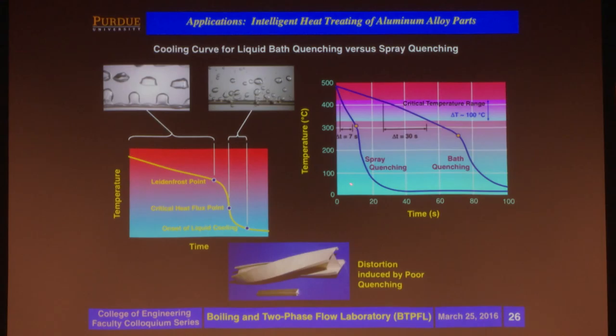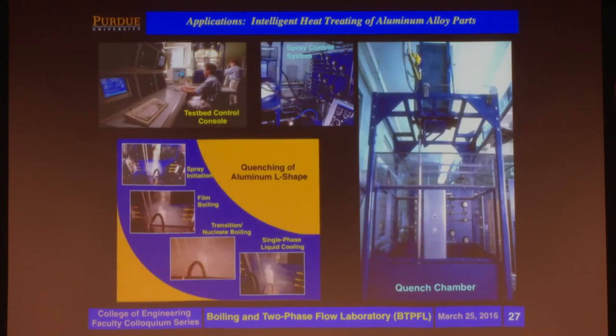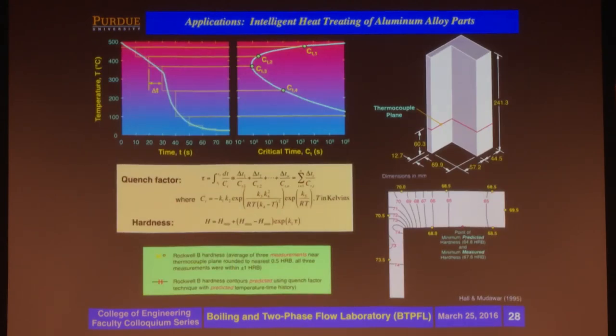Not only to speed up the quenching process, but also to achieve control, as I'm gonna show you. And we built a test bed for this purpose, where we have a furnace and we bring the part after being heat treated and quench it within this chamber that you see right here. And what we were able to do is combine our understanding of the quenching process with metallurgical transformation theory in order to optimize the impact of the quench on the material properties, namely hardness and strength of the part.